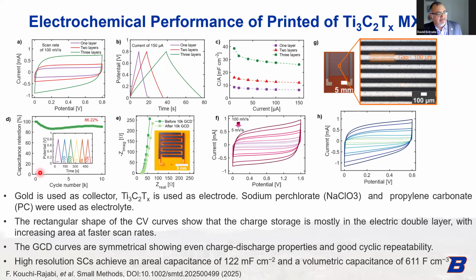So we did do some cycling as well. We did about 10,000 GCD cycles. We're retaining about 86% of the capacity. The drop is due to just a little bit of increase. I should say we're using sodium perchlorate as our electrolyte for these curves, but we also did an aqueous gel electrolyte as well. This curve tells us the storage mechanism for this MXene.